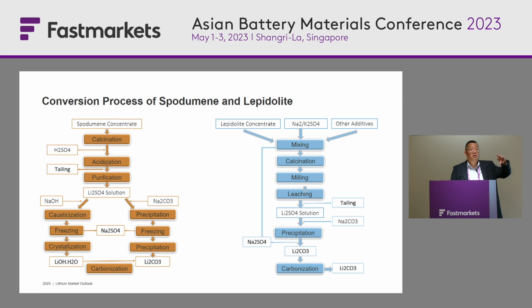And by calcination, you will see the phase change of the mine. And it will be molten or melted. And then you break this melted calcinated ore apart and grind it. And then you have small particles, and by leaching, okay, by water, you take the lithium sulfate solution out, and then you have different purification processes to get rid of calcium, magnesium, or whatever it is. And then it's a purified lithium solution.